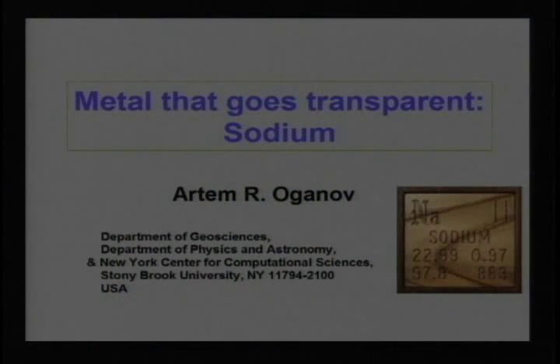Let me share with you results of our recent study which was performed by an international group of authors in which I was involved, and which resulted in an unexpected prediction, which we also confirmed experimentally. Our prediction was that sodium, one of the best metals, under pressure becomes a non-metal, and so much non-metallic that it even becomes a transparent dielectric.